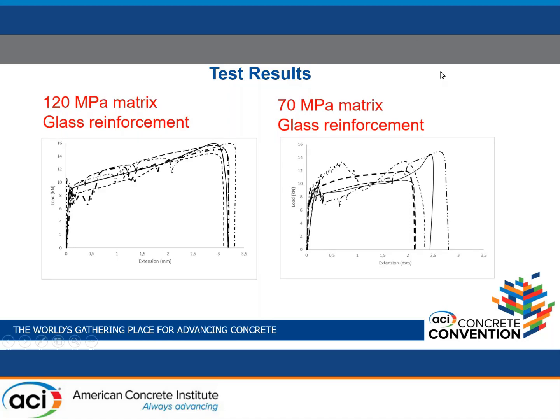This slide shows the glass reinforcement in two different matrices. If we compare the performance of glass fabric in UHPC and 70 megapascal matrix, the glass fabric reinforced UHPC matrix showed slightly higher load values, while showing slightly higher extension as well.